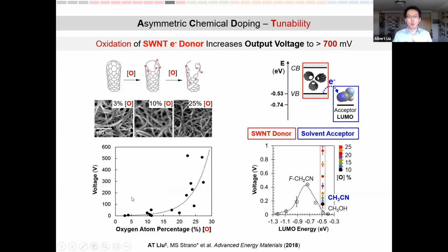In this case, what we're doing is by oxidizing our carbon nanotube lattice, we're lowering its Fermi energy, making it more and more easy for the electron transfer to occur, even for a single solvent acceptor, in this case, acetonitrile. As you can see from the plot, increasing the oxygen doping level onto our carbon nanotube will actually increase the voltage production up to 700 millivolts for acetonitrile. Higher oxidized carbon nanotube generates more voltage for acetonitrile asymmetric chemical doping.